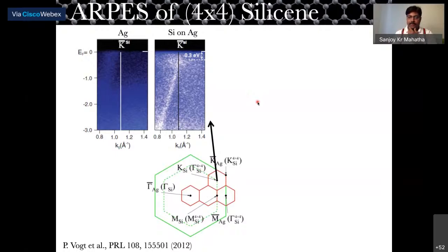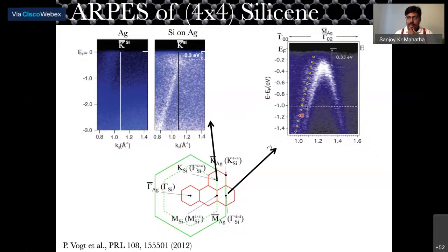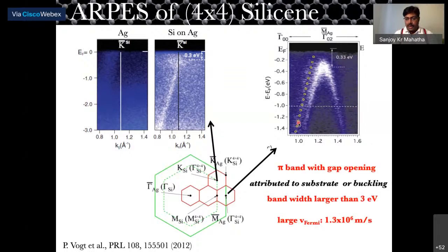And then in another paper, they claim that at the M point of the silver, which is also equivalent to the K point of silicon, they could also see another parabolic band, which they also claimed is a silicene Dirac cone. The bandwidth was larger than 3 eV, and they claimed the Fermi velocity of this band is 1.3 times 10 to the power 6 meter per second, which is even higher than that of graphene.